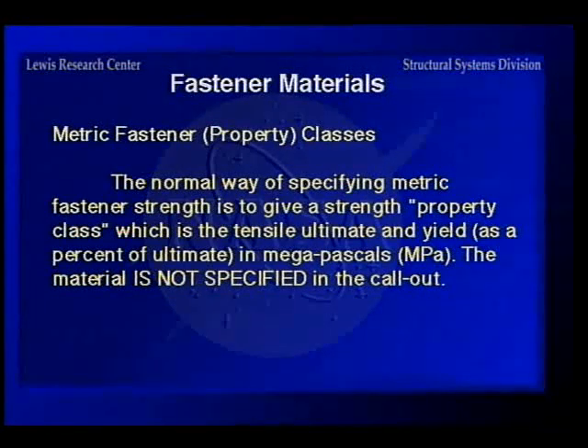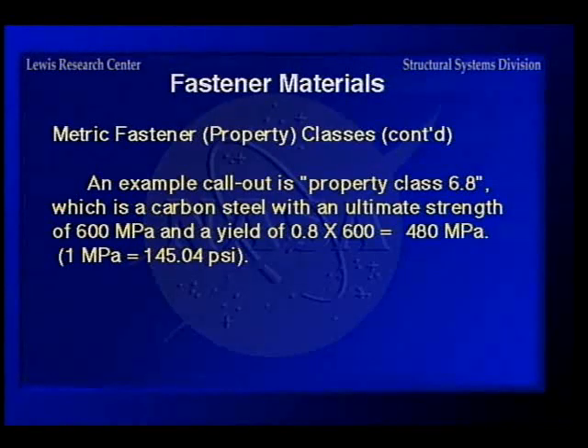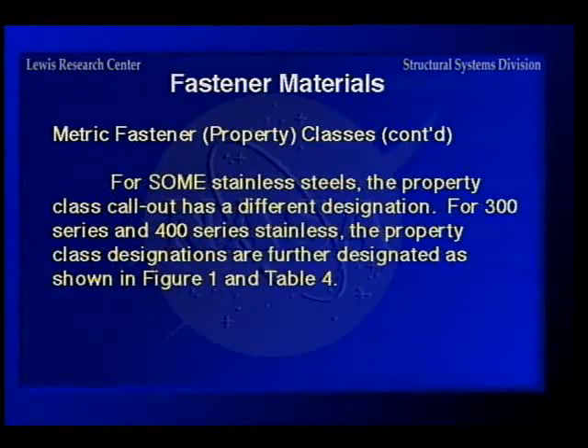On the property classes is the way that they specify the strength, which is a tensile ultimate, and then yield as a percent of the ultimate in megapascals. And a megapascal is 145.04 psi for any of those who need to convert. Now, the material is not specified in the call-out, so you have to specify the material yourself, or otherwise you don't know what you're getting. So if you have a property class 6.8, it's a carbon steel of some kind with an ultimate strength of 600 megapascals and a yield of 0.8 times that, because that's where the 0.8 comes from. Now, for some stainless steels, they don't use those rules, and so I have a table further down the line here that shows the peculiar type stainless steels, the way they're called out in the metric system.